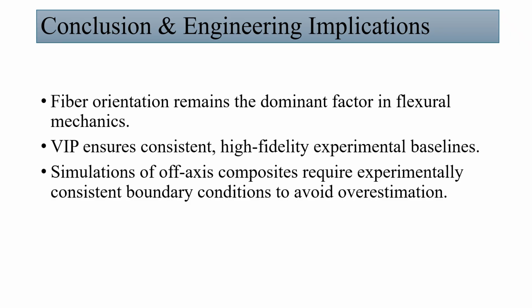In conclusion, this study reaffirms the dominant role of fiber orientation in flexural performance and the effectiveness of vacuum infusion processing for producing reliable laminates. Most importantly, our numerical evaluation highlights a critical pitfall. Utilizing standard rigid boundary conditions for simulating thin off-axis composite structures leads to artificial stiffening and inaccurate predictions. If we want reliable digital twins for aerospace design, our simulations must allow for natural kinematic couplings like bending and twisting.